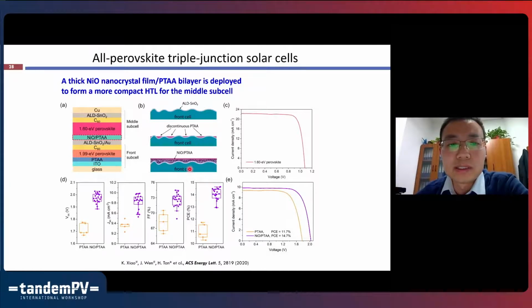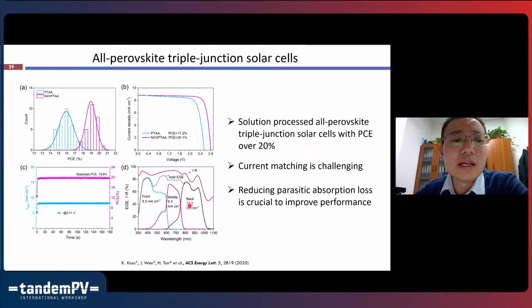So later we found a strategy: we can first spin coat a nickel oxide based nanocrystal layer to fill the valleys of this rough surface. Then we get a better film for the PTAA hole transport layer. Through this strategy, we can get much higher open circuit voltage and fill factor values. Finally, we can get reasonably good triple junction solar cells. The efficiency is almost 20%, and the fill factor value is quite high, above 80%.